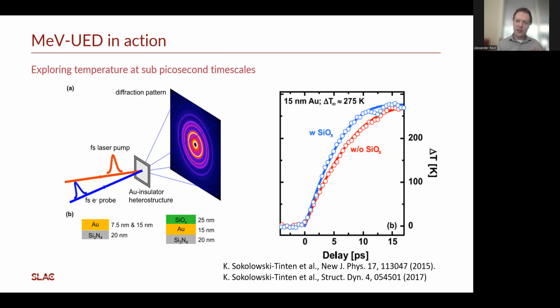And this can be related to an equilibrium temperature. And so by combining all of this, we can actually get this time versus temperature map for the various samples. Here you can see how the sample with a silicon dioxide cap actually has a faster transfer of energy from the electronic system to the lattice than one without. And so here we're able to measure the dynamics of these processes.